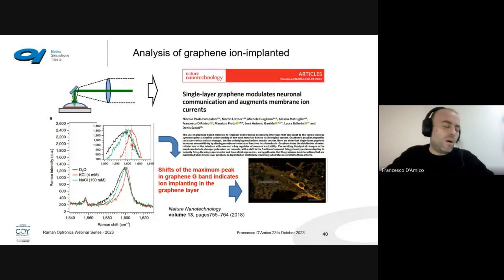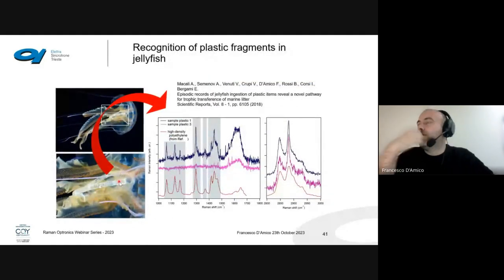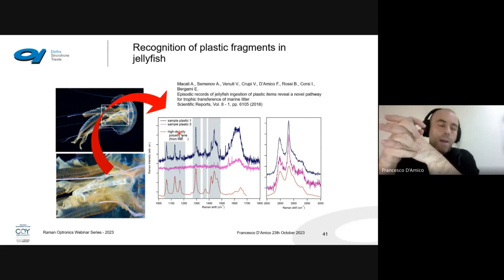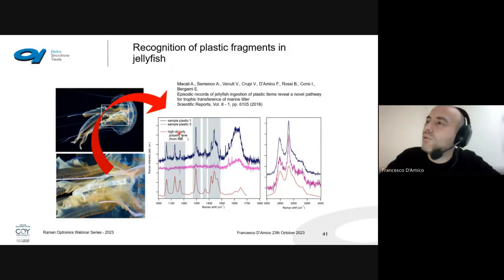We are at a spectral resolution of 1 inverse centimeter, really measured at a resolution of 1 inverse centimeter. We can monitor shifts in peak position as well as in the peak line shape, demonstrating this interaction. Then, just to pass to other topics, we have used UV resonant Raman scattering to recognize plastic fragments in jellyfish, identifying the spectrum of high density polyethylene in jellyfish. Could these measurements be done also with visible Raman? No, because in this case we have a dirty sample, and the measurements with conventional Raman were affected by a huge amount of fluorescence, not obtained by employing UV radiation.